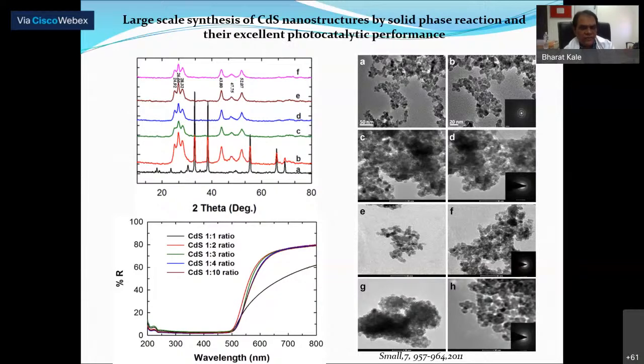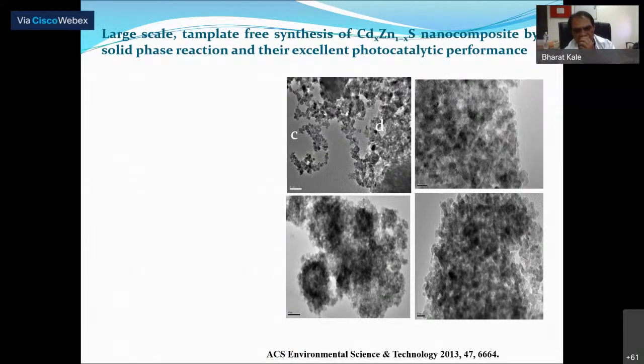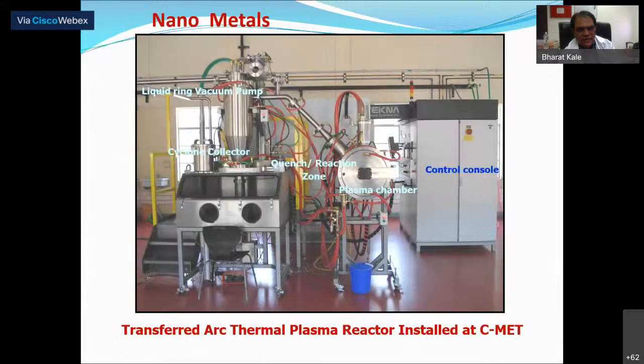Typically you can see that the size is maybe 5 to 20 nanometers, and quite uniform. Again, the same combination of cadmium sulfide and zinc sulfide with tuning of the band gap also gives a good particle size, and in huge quantities if you want to make. We can make nanometals, nano oxides, and nitrides using this plasma reactor.